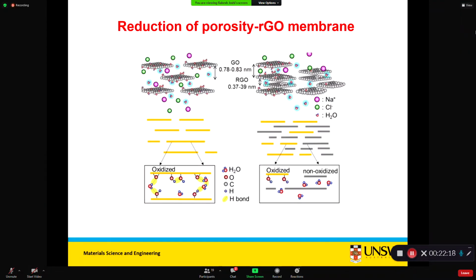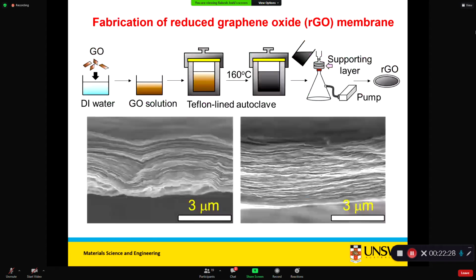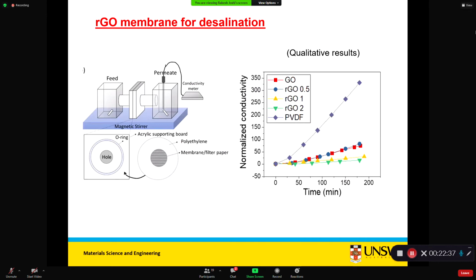Then we thought of changing. We were evolving our work with graphene oxide. So we thought of reducing the porosity, to see if we could go for desalination, and we did it using a hydrothermal method. We made RGO membranes and could get a porosity of less than 5 angstrom, and we did some conductivity tests for sodium chloride, and these membranes are quite stable. I'm not showing the real results because I have another industry project with an American company on removing salt ions and smaller chloride ions. The qualitative results show that if you tune the porosity, you can really control the salt rejection.